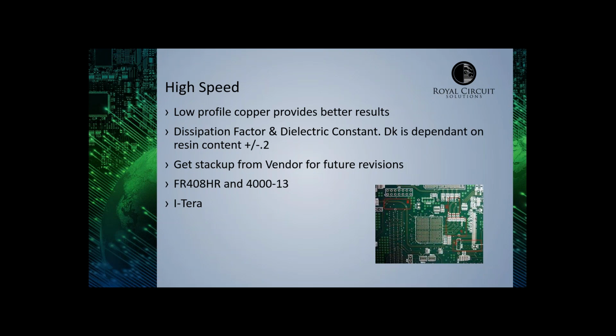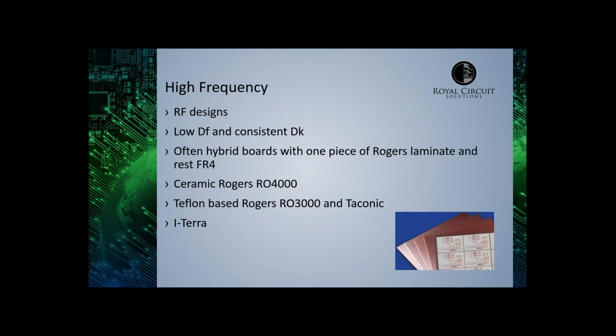High frequency boards, of course, are for RF designs. They usually have low DF and very consistent dielectric constants within that group. Generally with these high frequency boards, they'll be done as hybrids with one piece of Rogers laminate and the rest FR4. Ceramic RO4000 is a common one from Rogers, of course, and you'll mix that with FR4. You'll have a cap of Rogers, and then the inner layers will all be FR4.